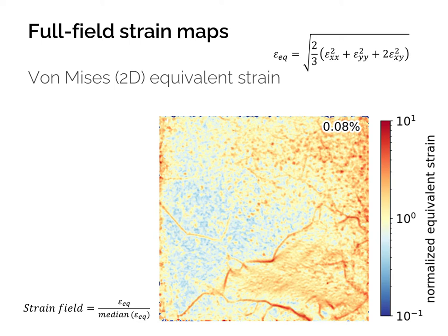To illustrate the evolution of the strain field, we use the Von Mises equivalent strain, which is the equation here that combines the different components of the two-dimensional strain field. The equivalent strain is represented normalized by the median strain and using a logarithmic scale, so that values up to 1 in blue tones represent areas strained below the average, while values above 1 up to 10 in red tones represent strain values above the average, and therefore strain localization. Unless explicitly stated, all maps illustrated here are incremental strain maps — that is, the accumulated strain in 10 minutes of creep — with the macroscopic finite strain always indicated in the top right corner of the map.